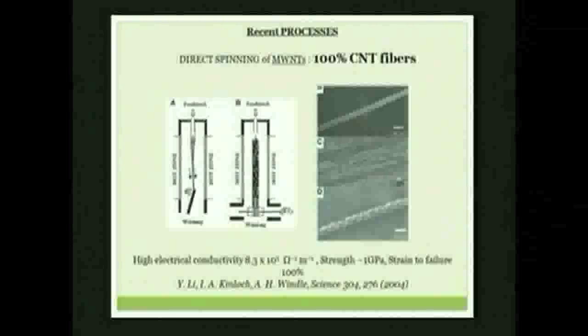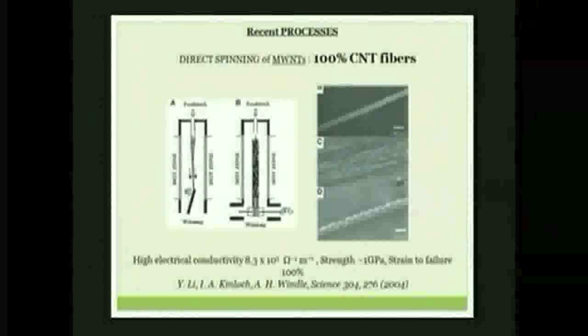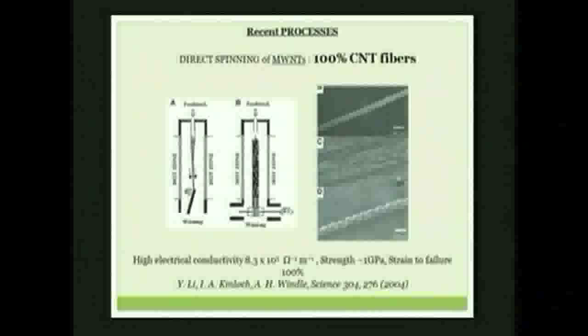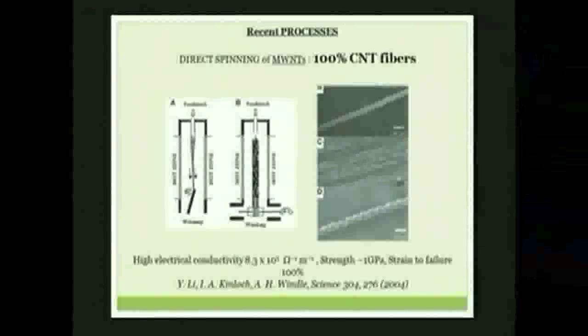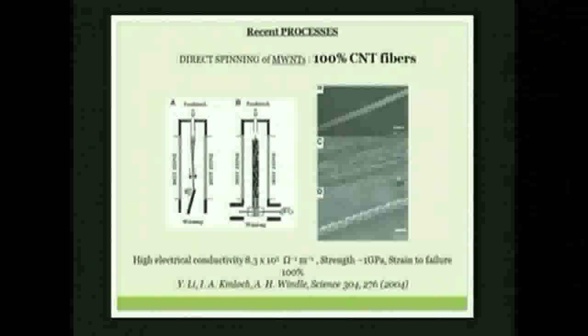You can find more recent processes to make nanotube fibers, like direct spinning of carbon nanotubes. With this kind of process, you can get 100% nanotube fibers. These processes always work like this. This is the furnace in which you produce the nanotubes. And you directly pull the nanotubes at the exit of the furnace, and then you can pull several nanotubes together and make 100% carbon nanotube fiber like these ones. These are nice carbon nanotube fibers composed of only carbon nanotubes, very well aligned. This is the reason why you have high electrical conductivities, high strength, and high strain to failure also. This is not really scalable. It's not easy to upscale this kind of process.